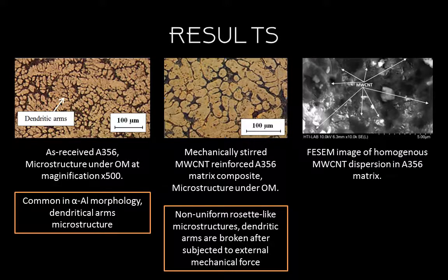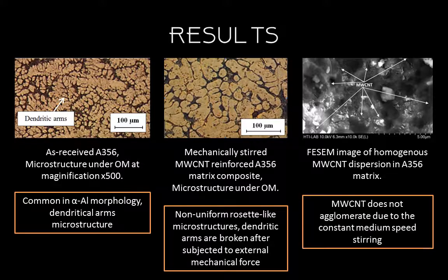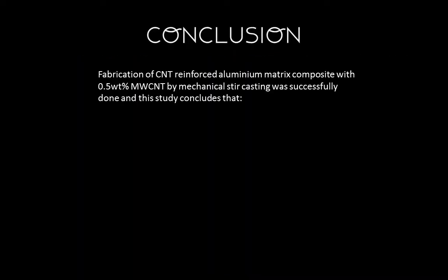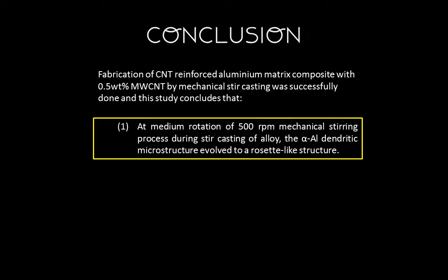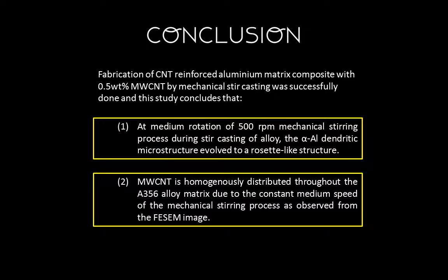The third picture is the FESEM image of homogeneously dispersed MWCNT in the matrix, proving that the MWCNT does not agglomerate due to the constant medium speed. It can be concluded that the fabrication of the composite is successful. At medium rotation or 500 rpm mechanical stirring during stir casting, the alpha aluminium dendritic microstructure evolved to a rosette-like structure, and MWCNT is homogeneously distributed throughout the A356 aluminium matrix.